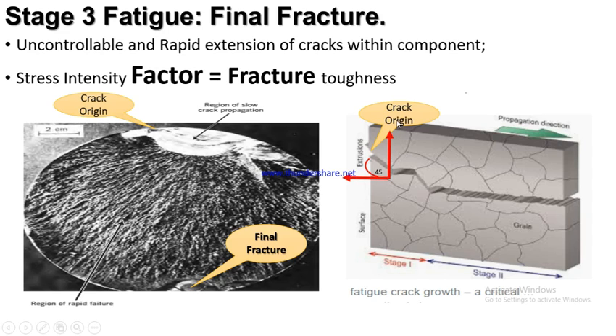How do we know that the crack initiated from this particular place? Especially when the material is experiencing tension, we find that there's a tearing which is nearly 45 degrees to the surface of the material. At that particular place, we can easily identify that the crack initiated from that surface of the material. As the crack begins to propagate, fatigue is liable to occur, which is the stage we call stage 1 fatigue, stage 2 fatigue, and finally the final stage of the fatigue is this particular place where the fracture is going to take place.